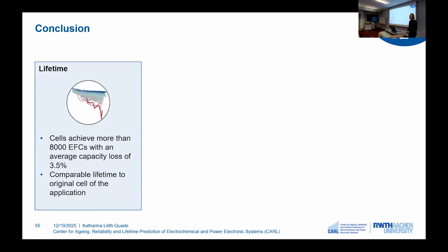So let's summarize the first chapter. In this chapter, I presented an experimental aging study of early commercial sodium-ion batteries, and we saw quite remarkable lifetime behavior, with some cells having reached more than 8,000 equivalent full cycles, with an average capacity loss of 3.5%. In total, we can say that this lifetime is very favorable for our high-power application.